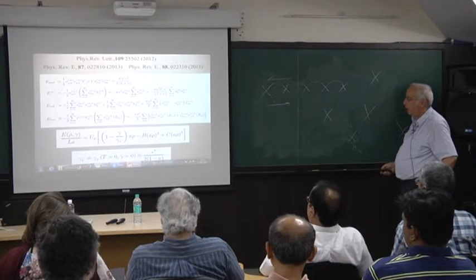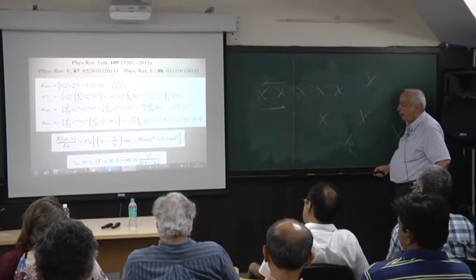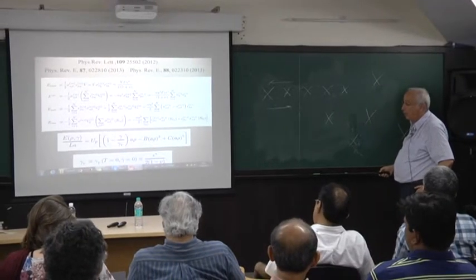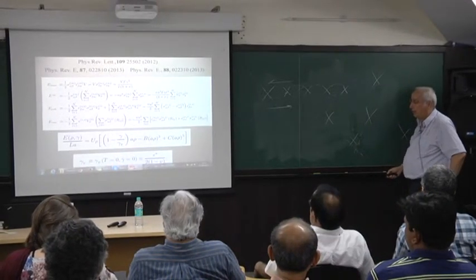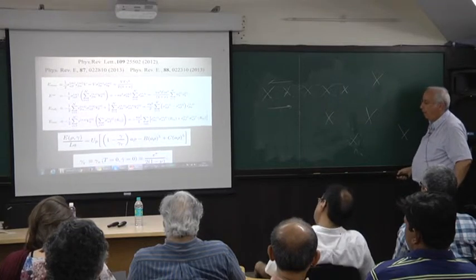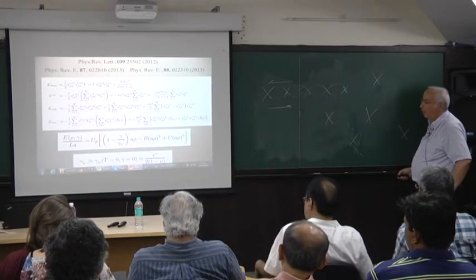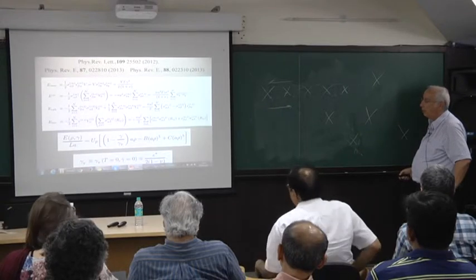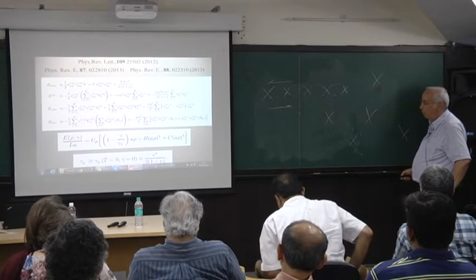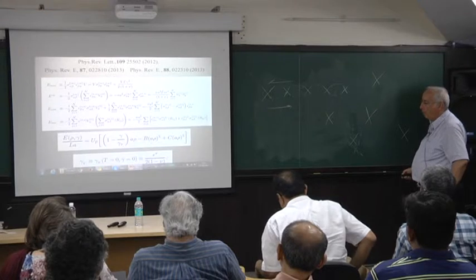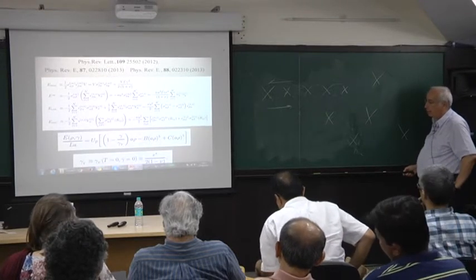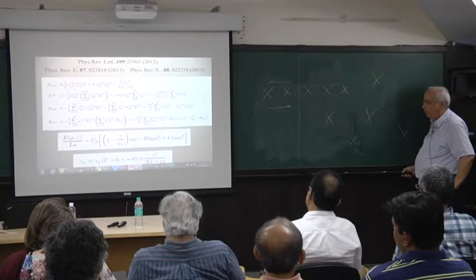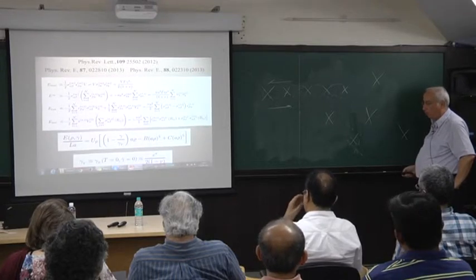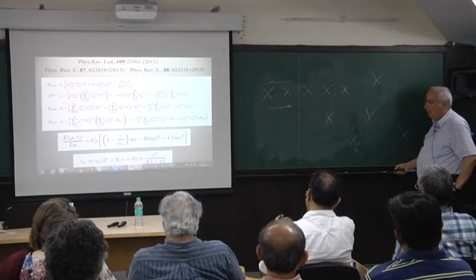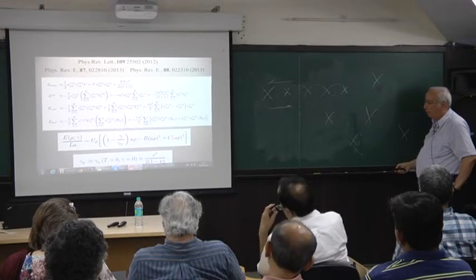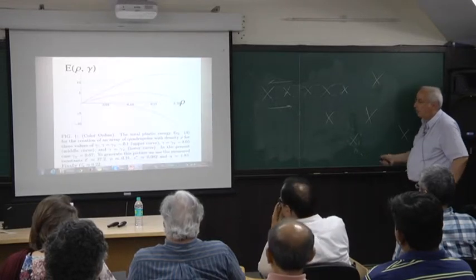Firstly, I have to say that this gamma y is not a parameter. It is exactly computable in this theory. And gamma y, which I'm going to call the yield, or let us say the critical value when temperature is zero and when the strain rate is zero, goes like the eigenstrain epsilon star over 2 minus 1 mu, where mu is the Poisson ratio. So this is known, and I can compute it. And now let me show you how this looks. So this looks like this.